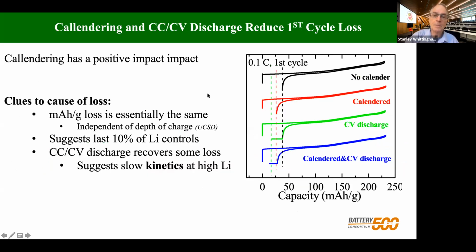So what is important is something that we call calendaring. Let me go over to the right-hand side here. This is a typical charge and discharge, charged at C/10, so this is 10 hours. All lithium-ion batteries are charged and discharged at a very low rate, typically C/10 or even lower, to break them in and to form protective layers, called SEI films, for the first few cycles. So this is where we get this first cycle loss.